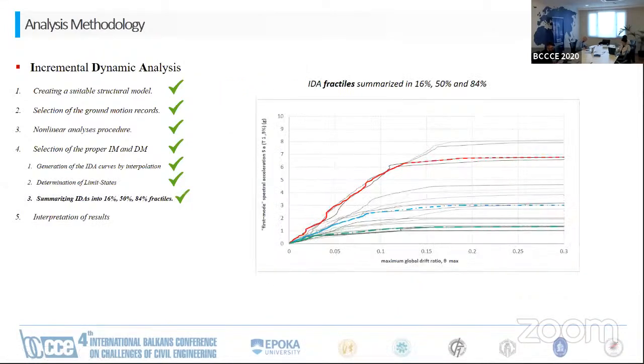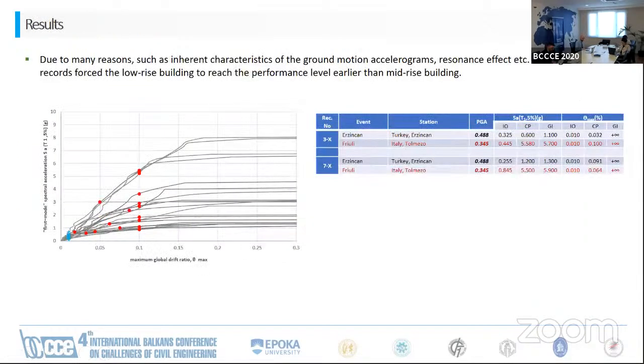It is also proposed by researchers that in order to interpret the results, fractiles give much information, summarized as 16%, 50%, and 84%. We have observed that for some cases, some of the records actually forced the low-rise building to fail before the mid-rise building, and this can happen due to many reasons, as for example, the inherent characteristics of the ground motion record, resonant effects, and maybe other reasons as well.